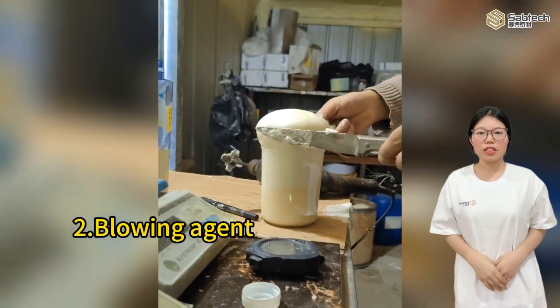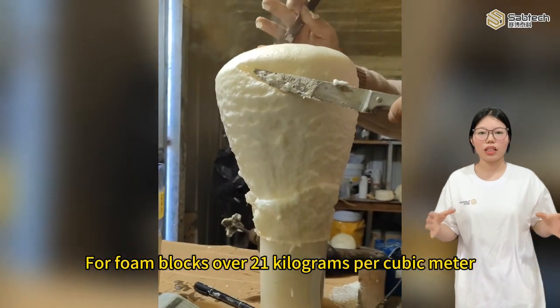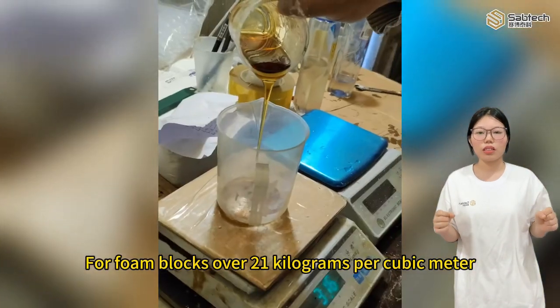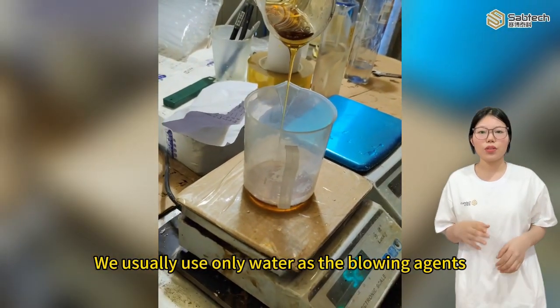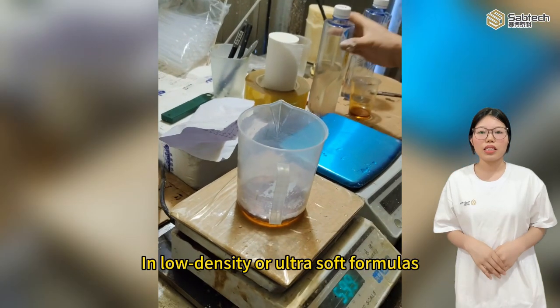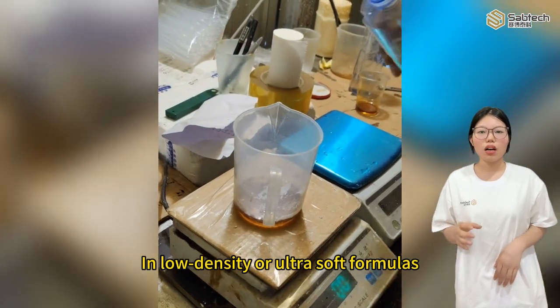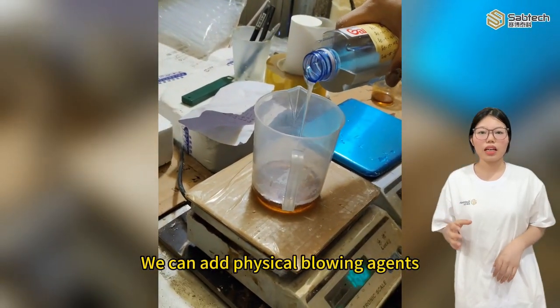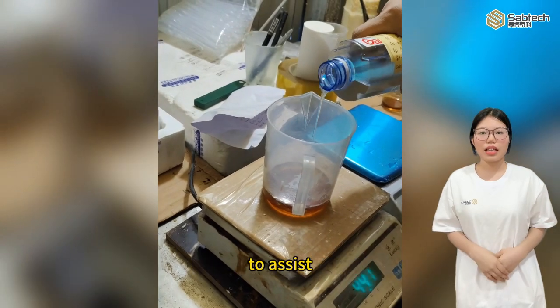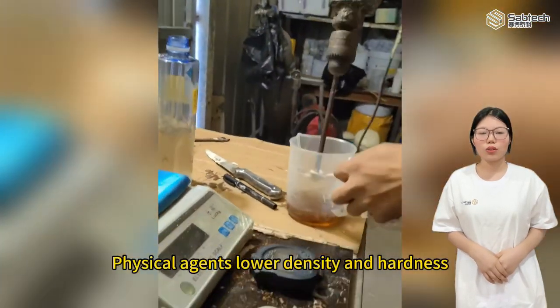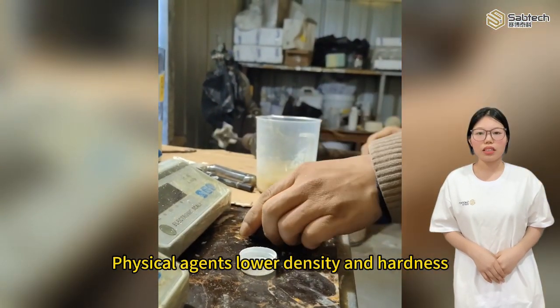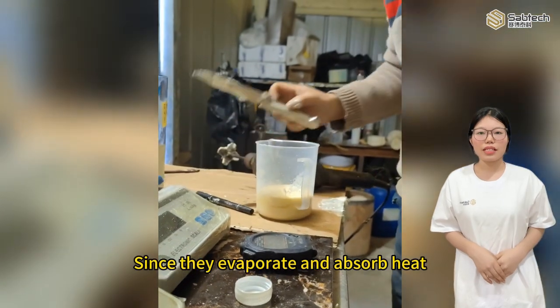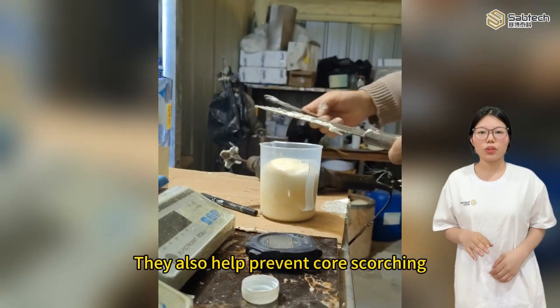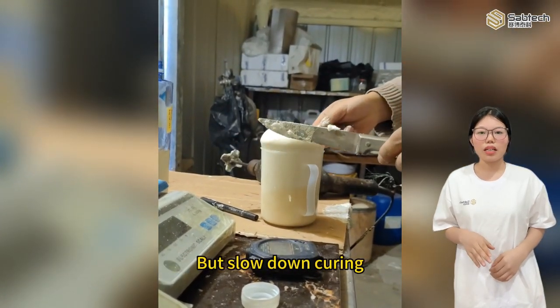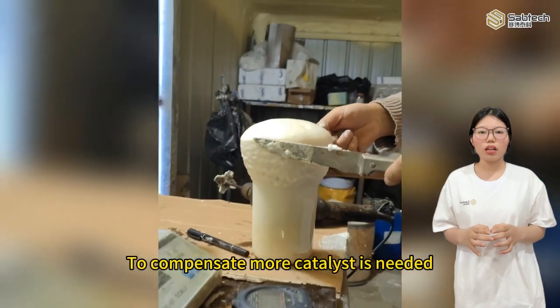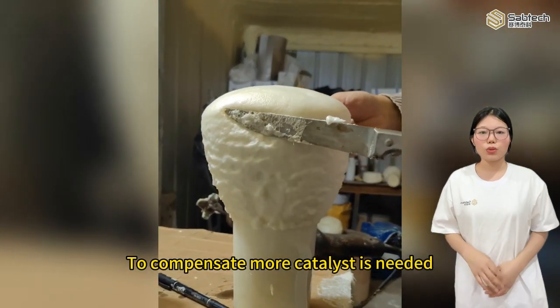Second, blowing agent. For foam blocks over 21 kilograms per cubic meter, we usually use only water as the blowing agent. In low-density or ultra-soft formulas, we can add physical blowing agents like methylene chloride or MC to assist. Physical agents lower density and hardness. Since they evaporate and absorb heat, they also help prevent core scorching, but slow down curing. To compensate, more catalyst is needed.